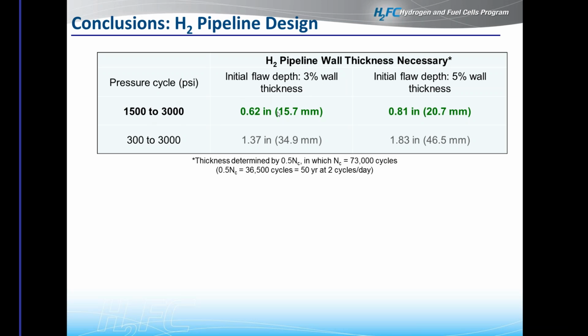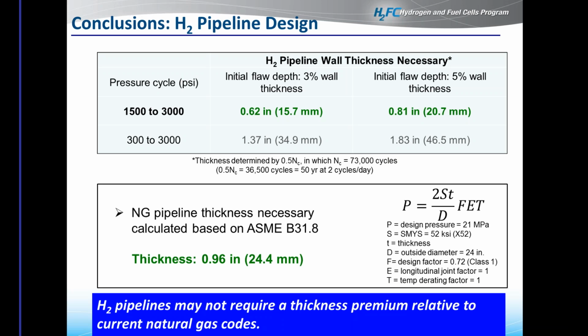And so to give us some frame of reference, we looked at what the current codes are for natural gas. Those are outlined in the ASME B31.8 code. If we assume we have a pipeline that is an X52, where 52 relates to the yield strength, and we assume that we're operating this under 3,000 psi pressure, this is not a fracture mechanics-based approach, but the thickness that you are required to have for this pipe would be almost a full inch thick.